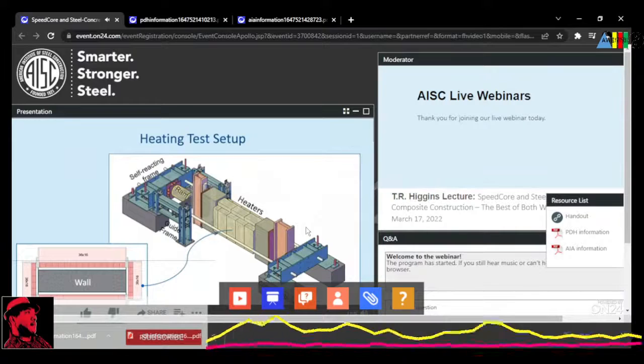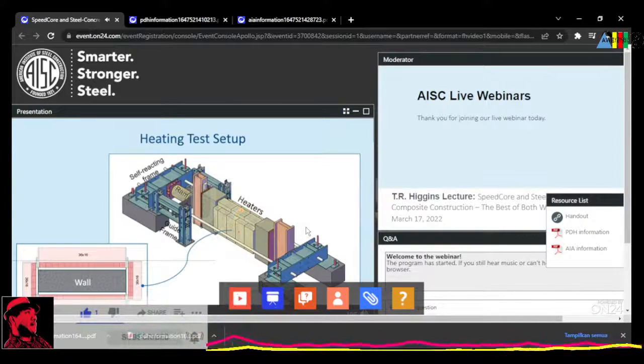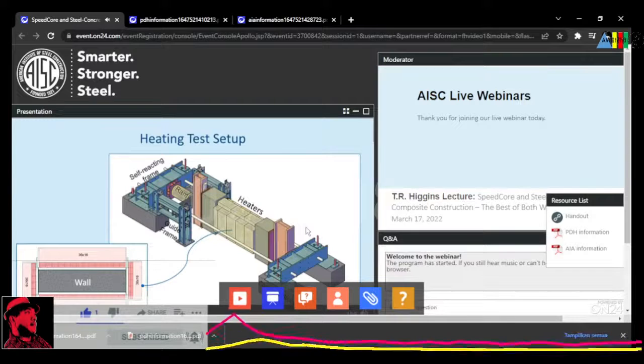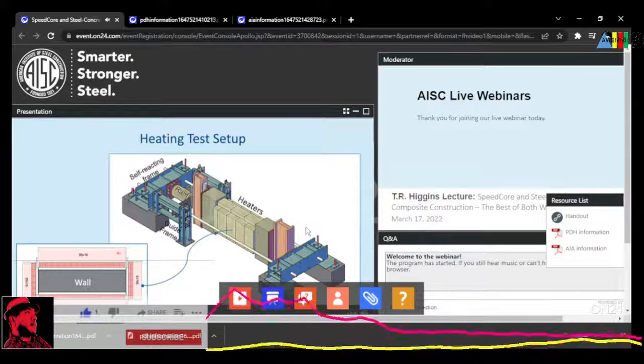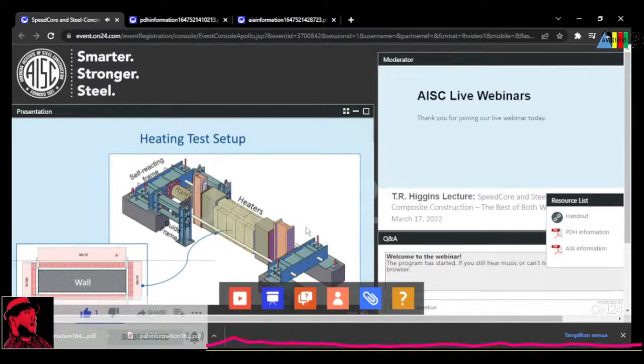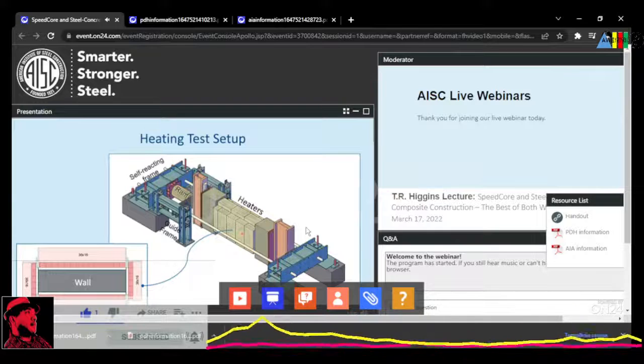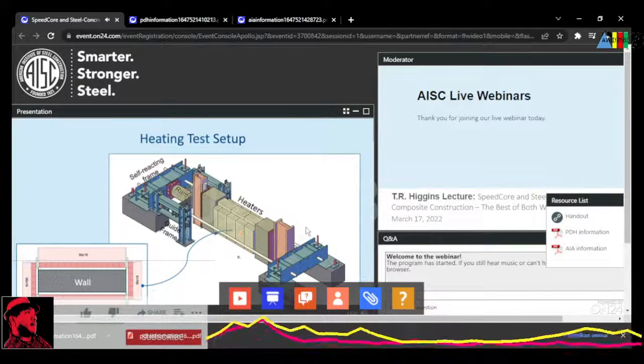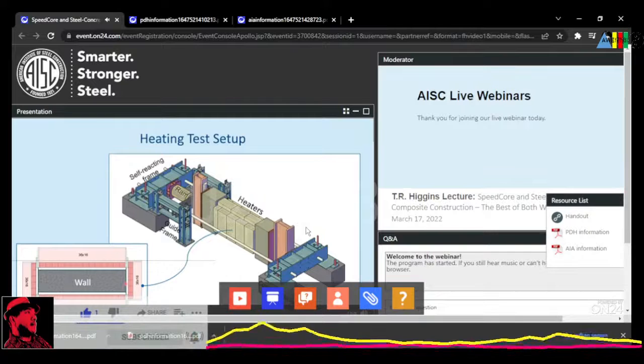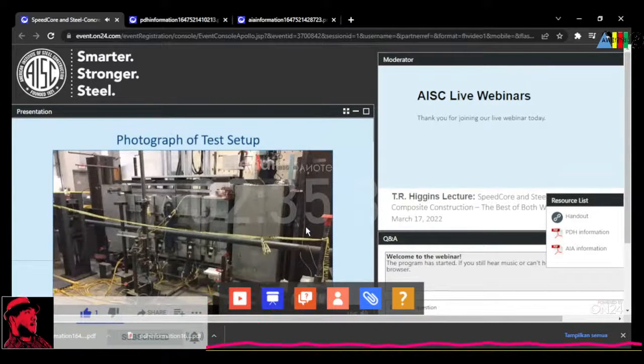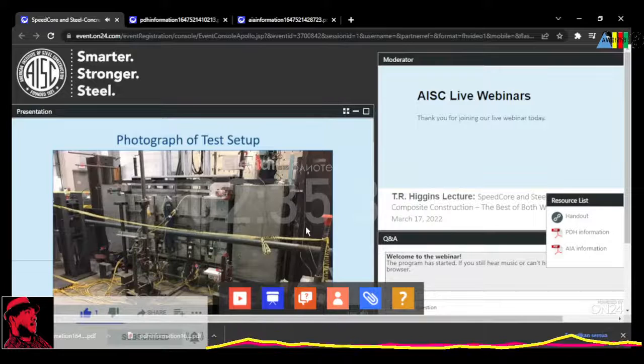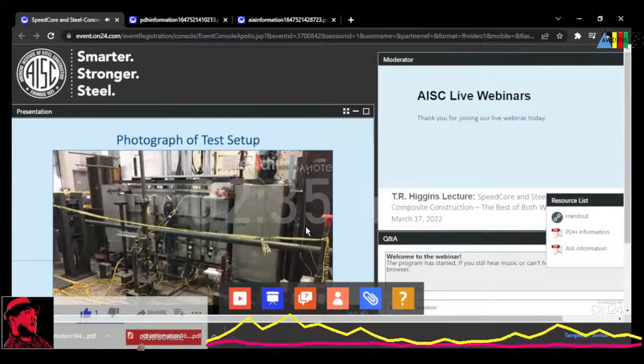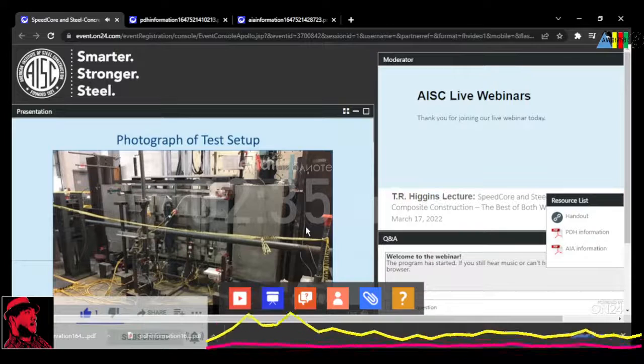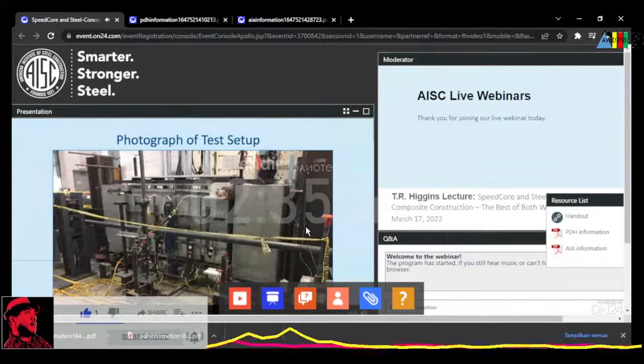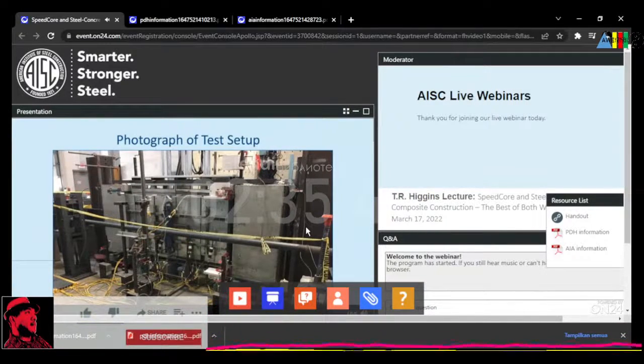Thermal loading was applied using ceramic fiber radiant heaters that surround the specimen completely. These heaters can be controlled to apply different surface temperature time curves. In these tests, they were used to apply the effects of standard fire temperature time curves directly to the specimen surfaces. This is showing a photograph of the specimen with the structural setup and the heaters all around it. Thermocouples and other sensors for measuring thermal and structural behavior can be seen.